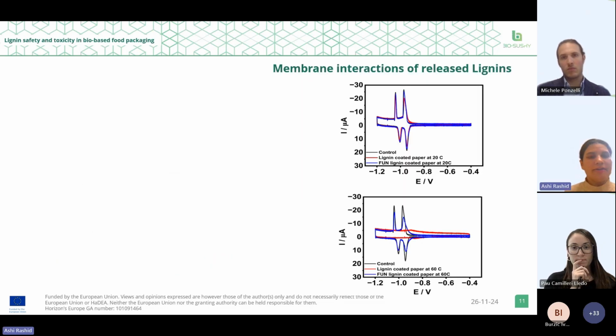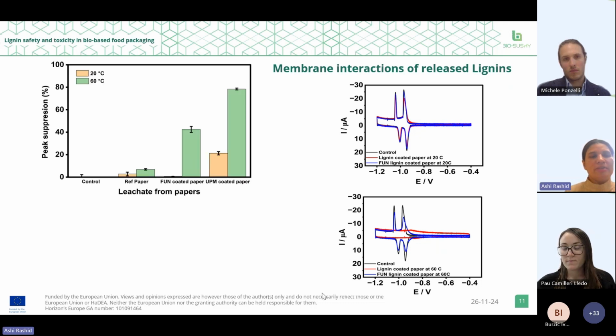Here I have presented some of the data from the released lignin, and these are the peak suppression plots of the leachates from the lignin and functionalized lignin coated paper, acquired at two different temperatures, 20 and 60 centigrade. From the peak suppression versus substrate plot, we can see the peak suppression is almost zero for the control, the phosphate saline buffer we are using, indicating the absence of any impurities in the system. So the system is very clean and can be used for assessment of membrane disruption caused by the leachates.